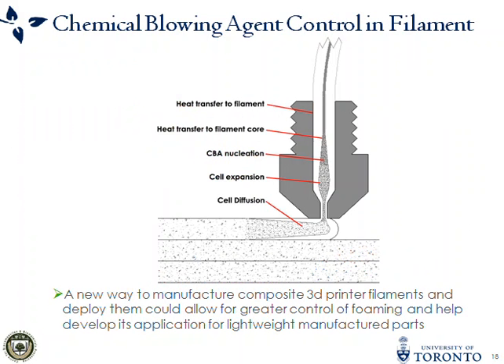So I made this diagram to show how a 3D printer filament with a dense core of chemical blowing agent can solve some of the problems and challenges with having chemical blowing agent in a 3D printer filament. Because if it diffuses very fast, it's such a short window of time, and it's a very small volume of material, that the gas can escape very easily. But my idea is to use a special process to concentrate the blowing agent at the core of the filament, so it has a better chance of diffusing properly while it's being deposited.